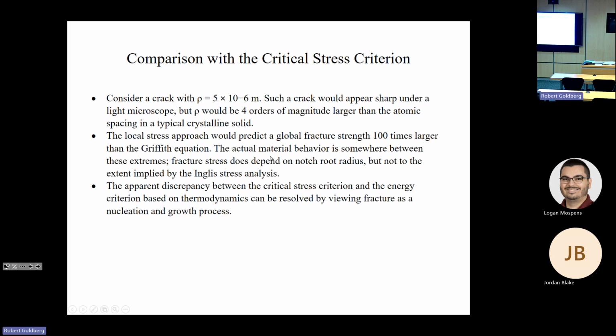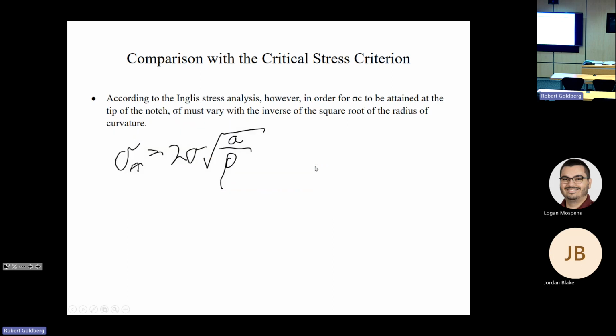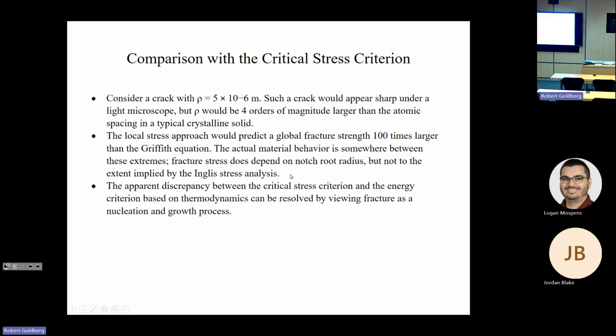As in many things, when you talk about approximations, the Inglis approach and the Griffith approach are bounds on the problem. So what happens is that the actual material behavior is somewhere between these extremes. The fracture stress does depend on the notch root radius, but not to the extent indicated by that equation. So the apparent discrepancy between the stress criteria and the energy criteria based on thermodynamics, you can resolve by viewing fracture as a nucleation and growth process.